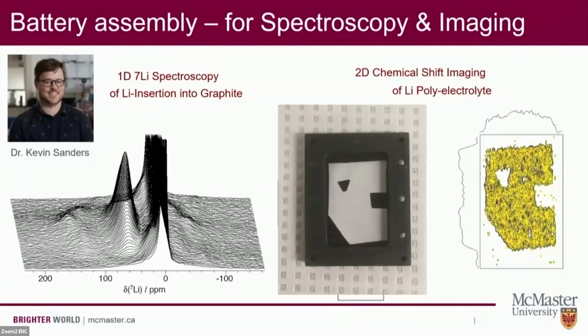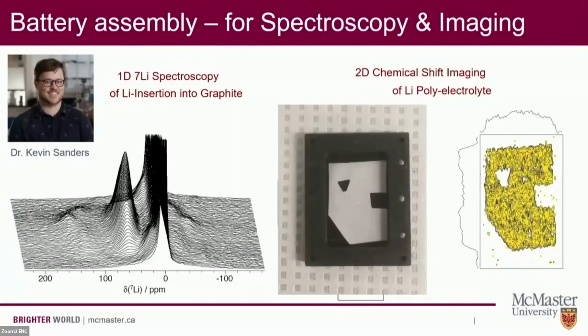In the case of the lithium plating studies, there's not as much paramagnetism there, but we already have really good chemical shift separation. So we rely on the wide bore spectrometer to be able to do the imaging and the diffusion sequences. So I don't think, at least in my lab, I have an opportunity to go beyond the field strength we're using. It's great to hear that there's a race for lower fields for those of us who have some really low field magnets anyway for paramagnetism. That's right.